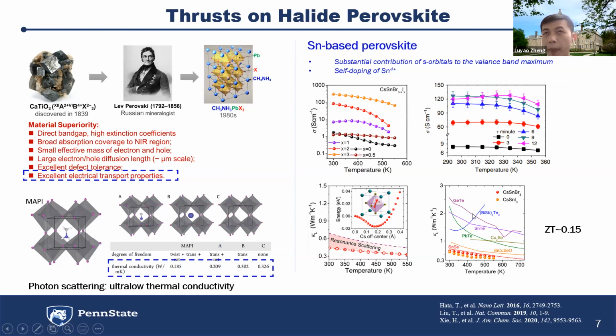But up to now, the record ZT value is about 0.15 based on this material. It's not as good as the state-of-the-art thermoelectric material, but it has huge potential and huge room to improve. So we can try to introduce some dopants or do some nanostructured processing of the material, and in the future we can probably boost the ZT value to over 1 or even higher than the typical or traditional thermoelectric materials.